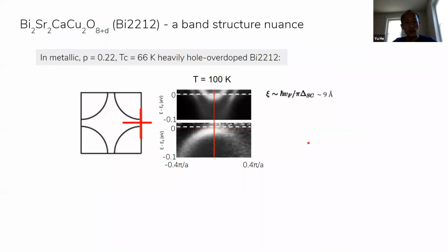But we notice there's a small band structure nuance, where if we look at the local band structure along the Brillouin zone boundary, we see that there is a very shallow Van Hove point, a very shallow local band bottom, or a very shallow band top if we look at the perpendicular direction, that are very close to the Fermi energy. And they're very flat. They're flat to an extent that extends almost to 30% of the linear dimension of the Brillouin zone.